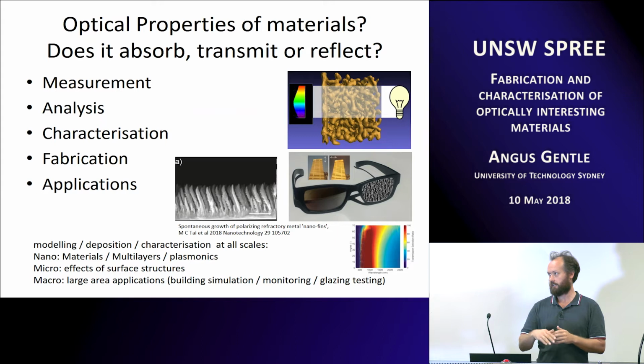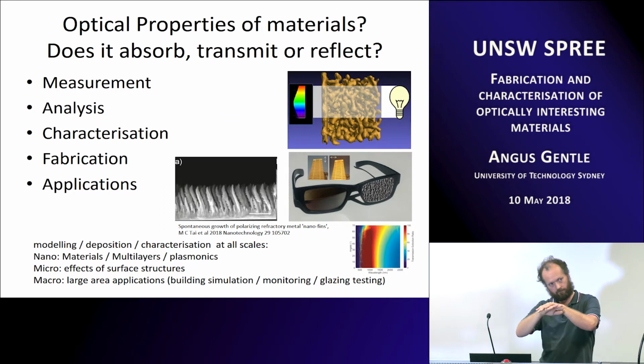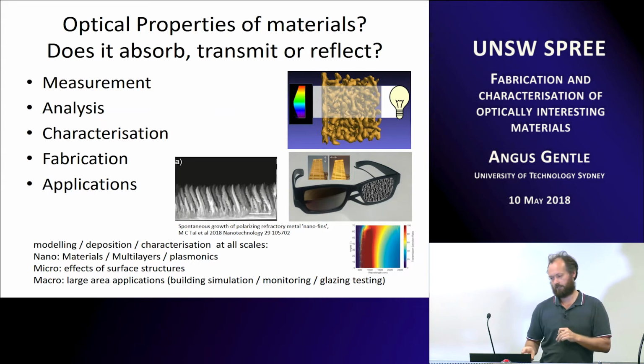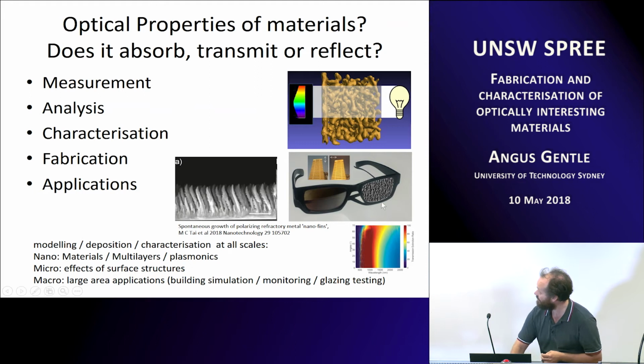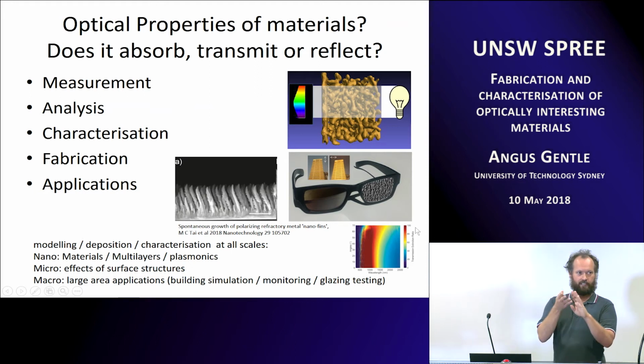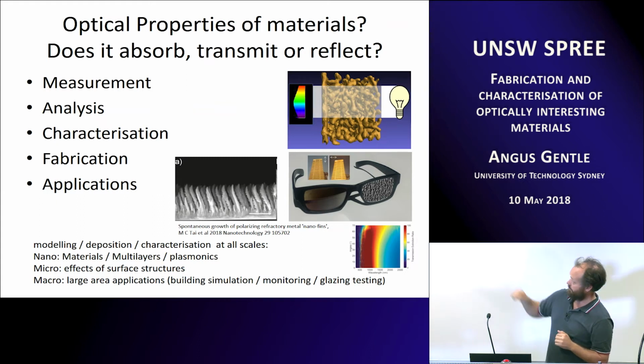So they're refractory, so you can heat them right up, very stable. They're also polarizing. So to start with, they've got a continuous metal film underneath, so you can do it as a self-assembled polarizer that reflects. We can de-alloy the aluminium out of it. So it's a combination of molybdenum and aluminium. De-alloy the aluminium out, and on that picture there, that's an SEM of the de-alloyed one. So it actually goes and aligns really, really well, self-assembled as a polarizer. And so above there, that's an image through these glasses.